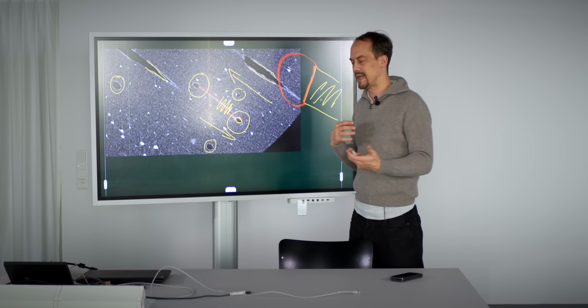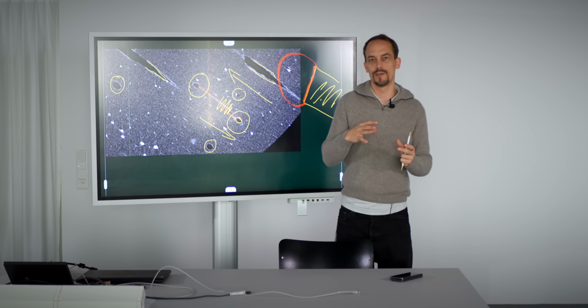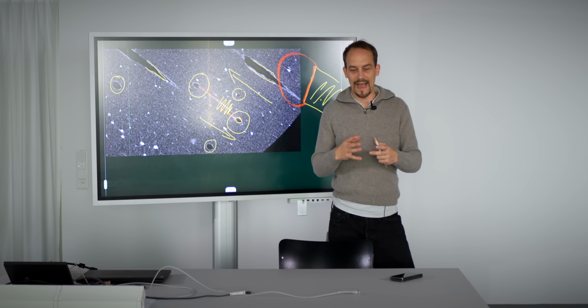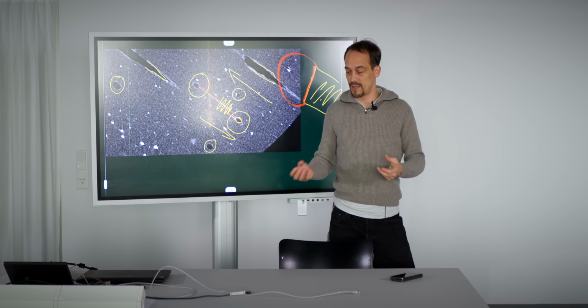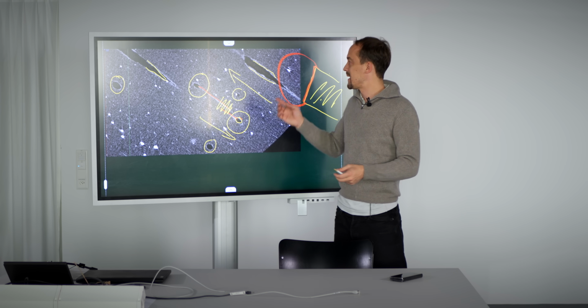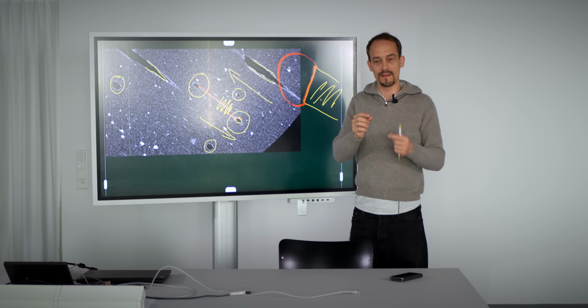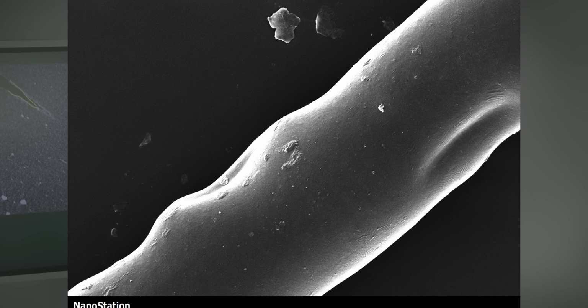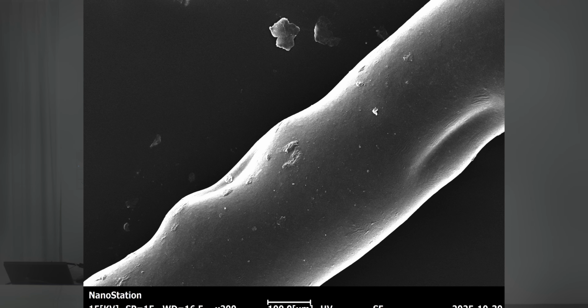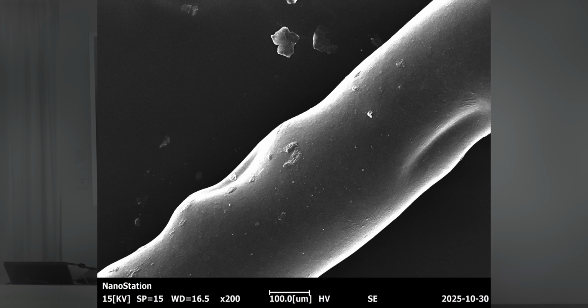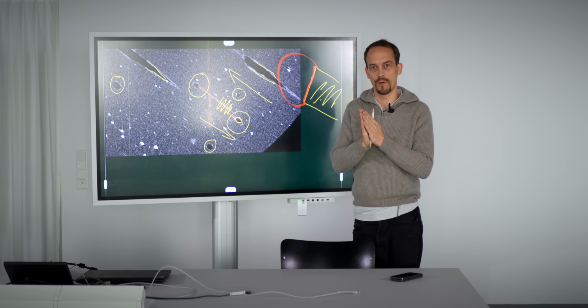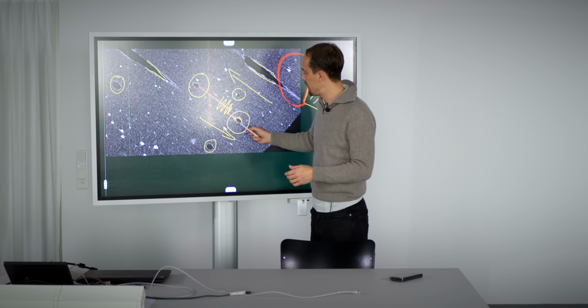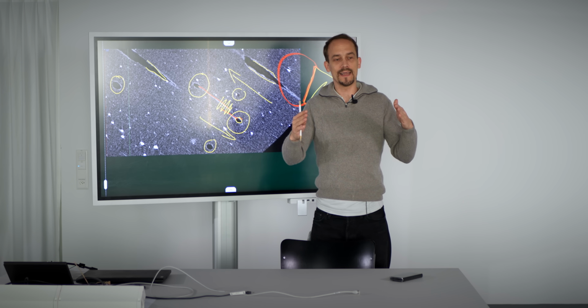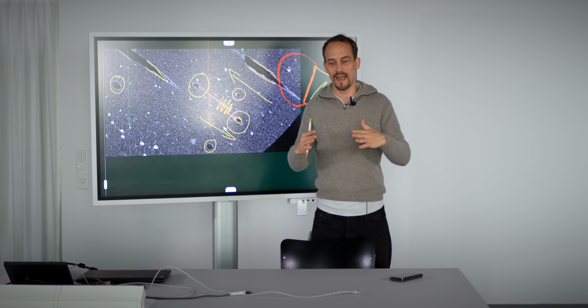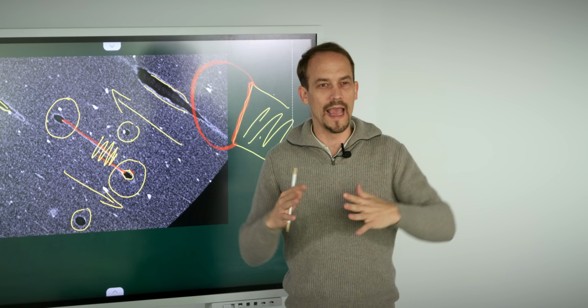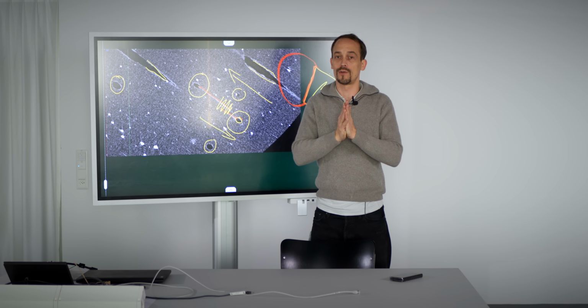And I think that kind of makes sense, because if we look at the microscopy images of PLA-CF, you see that the outside of the filament itself, the extrusion strand, is a wild mess. But here, if we look at the extruded strands that we did separately and photographed under great magnification in our microscopy, the surface of it is very smooth and clean. So I think the carbon fiber not only disrupts layer bonds, but it also has this cavity effect on the outside of the extrusion. And that is why in the last micro CT image we saw of PLA-CF, the edges touching each other were super edgy and not consistent at all, which also weakens the material further.